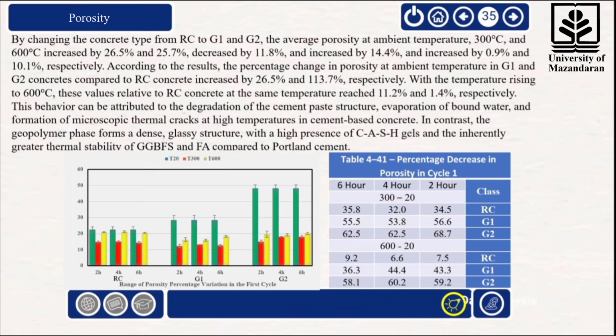This trend can be explained by cement paste degradation, evaporation of bound water, and the development of thermal microcracks in RC, versus the formation of a denser glassy phase within the geopolymer matrix. The presence of CSH gels and the inherent high thermal stability of GGBFS and Fa are considered the main factors contributing to the superior performance of geopolymer concretes.